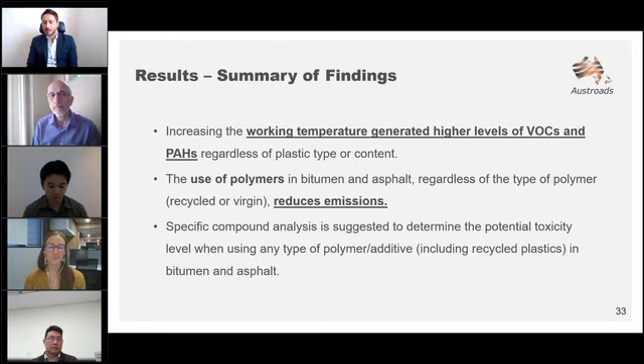You have seen probably the video where Dai was mixing it in the lab, and it was pretty much all covered by plastics, even at the 1.5%. So it becomes quite sticky and difficult to compact. It becomes a bit solid as a mix, not really workable. That doesn't mean that if you go up with temperature, like 190 plus, you can't still make it work.